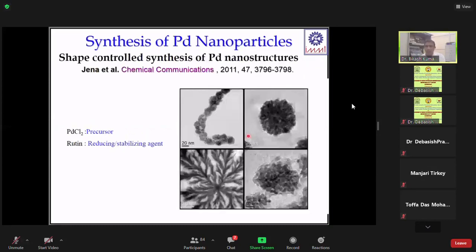I'm showing this because of how we can use small biomolecules for synthesis of very different shapes of nanoparticles. You can see we also synthesized palladium nanoparticles. You can see chain-like structures, fractal structures, dendritic structures and some porous structures, which we could synthesize using rutin as a reducing agent. Here we can increase the temperature a little, up to 80 to 90 degrees Celsius, so that it can easily reduce the palladium chloride. And you can see very beautiful different shapes of nanoparticles formed.